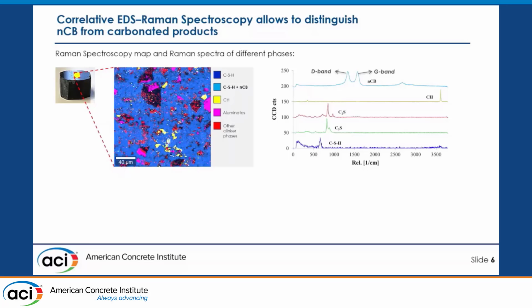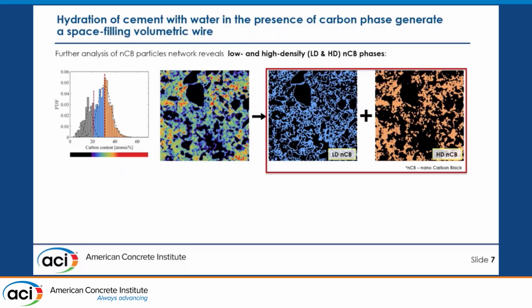That was very important because we wanted to distinguish nanocarbon particles from carbonated products, which both contain carbon. So EDS spectroscopy alone is not enough to give us this input. So here I'm presenting an EDS map of carbon content, which is separated already from the natural carbonated product, and we can see how it shows a space filling volumetric wire inside.